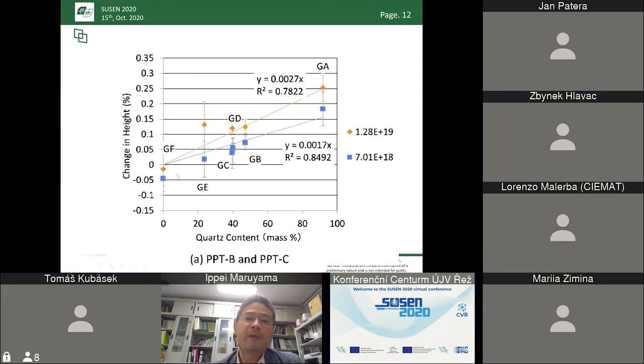And some of the aggregates don't follow the linear relationship. Probably this is due to the contribution of other rock-forming minerals such as albite. So therefore, we found that in the case of sedimentary rock, alpha quartz is very crucial for the expansion of the aggregate, which causes expansion of the aggregate and the degradation of the concrete.